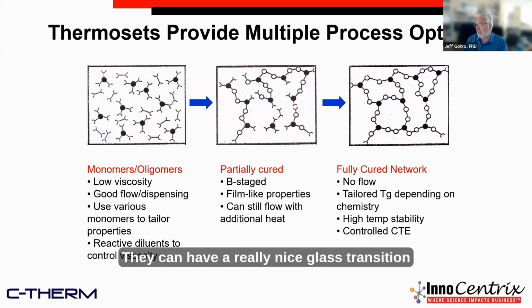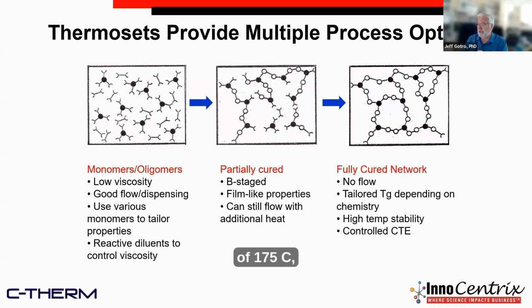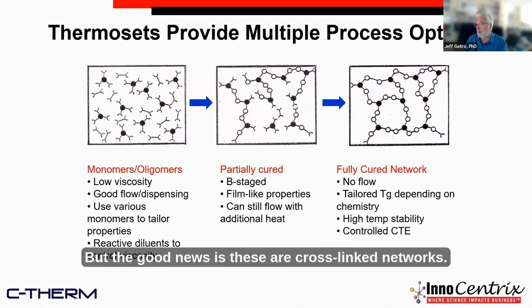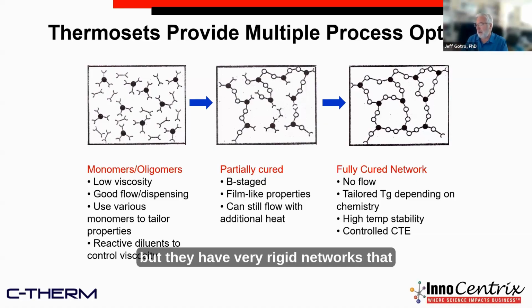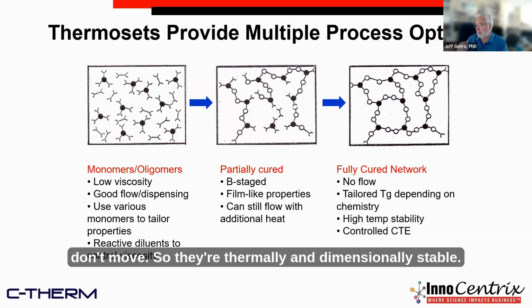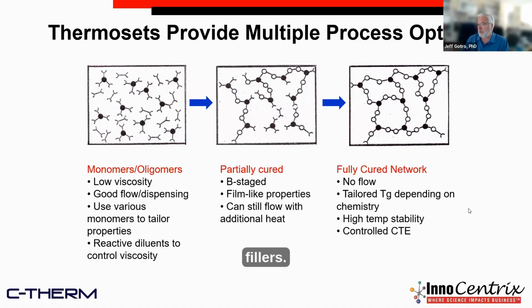They can have a really nice glass transition temperature depending upon what chemistry you choose. The reason these are used in electronics is because they're very thermally stable. If you have a glass transition temperature of 175 C or 200 C, you're going to need to get well above that to solder. But the good news is these are cross-linked networks, so they'll soften, but they have very rigid networks that don't move. So they're thermally and dimensionally stable. And like we talked about, you can control the coefficient of thermal expansion with fillers.